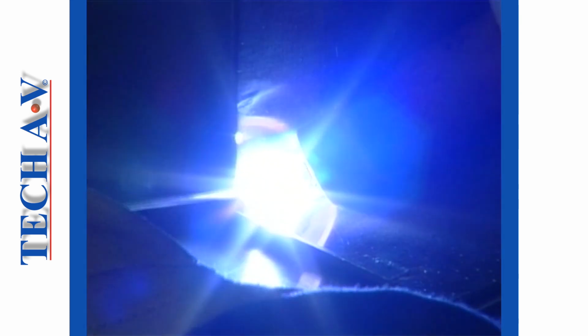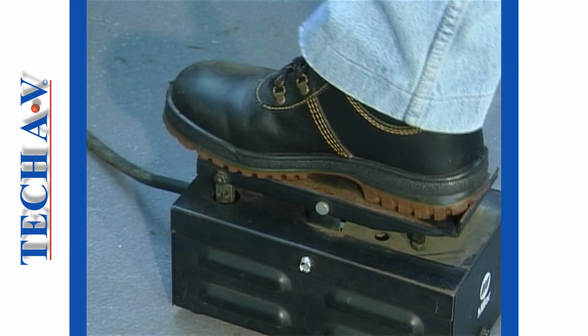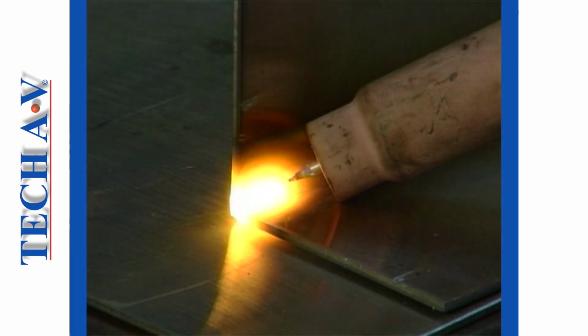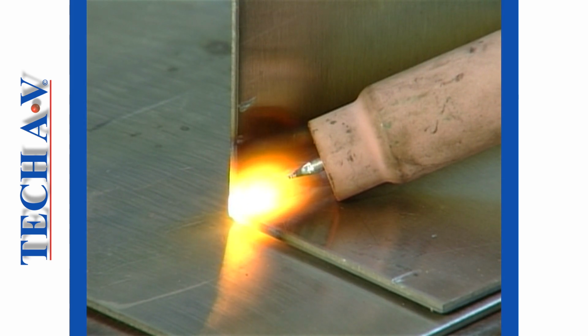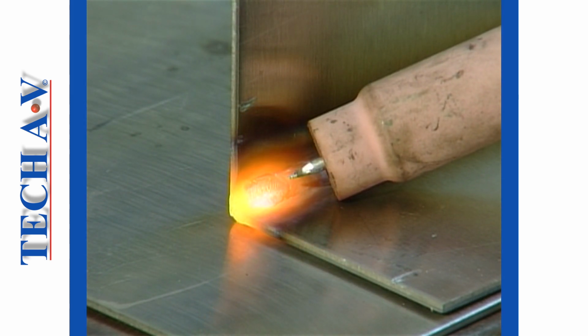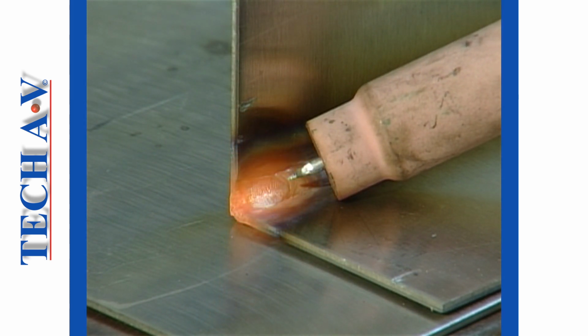The vertical plate, however, tends to heat up more rapidly than the horizontal, and as a result, the weld pool will tend to draw to the hotter area. With practice, you will discover that the arc should be pulled slightly to the lower section of the weld zone and the filler wire added low down into the pool. Allow the current to taper off at the end of the run and finish by bringing the arc back onto the bead. Allow the gas to complete the post-flow cycle before you remove the torch.